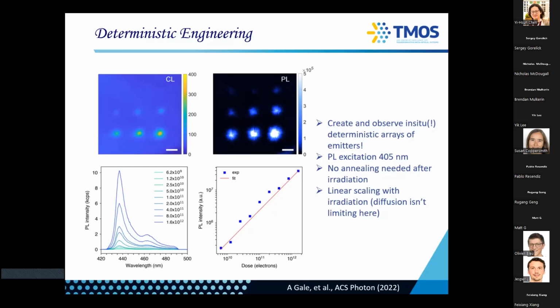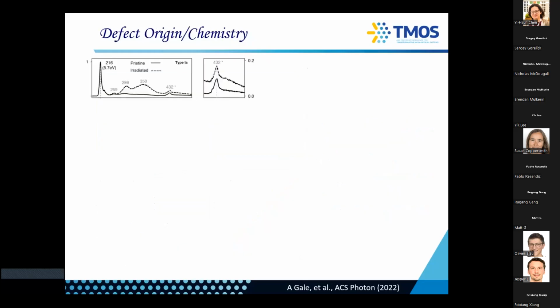So the question is what they are. We called up every person we know that can provide us with good, high quality hBN, and we did a bit of analysis. This is going to be a bit of a busy slide, so stay with me. The names are just different types of hBN. We don't really know what the difference is, but they are different types. Type 1A has a very strong emission in the UV. This is the exciton emission of hBN, at 6 eV. If you irradiate it with electrons, you would create these bands and this 432 emitter, which is not our emitter. Our emitter is always exactly at 436.